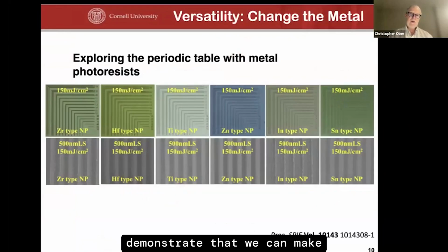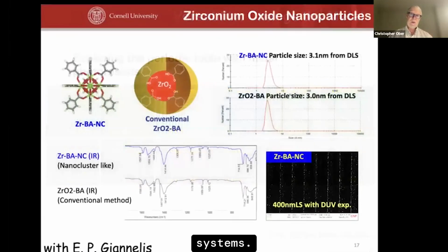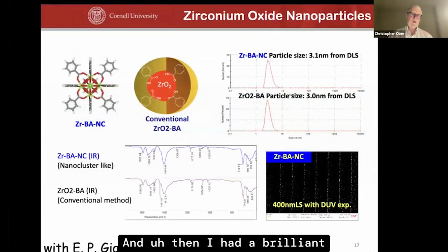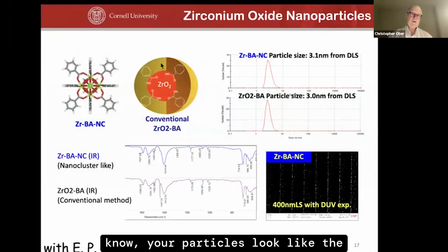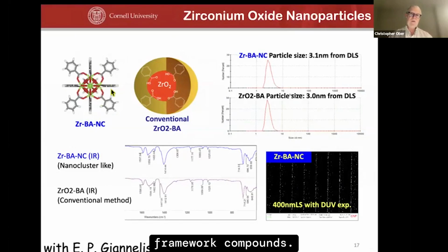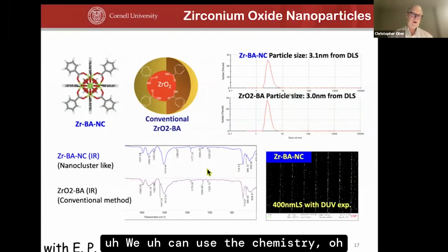And we also were able to demonstrate that we can make patterns with all kinds of oxides. This is with ultraviolet 248 nanometer exposures. It turns out at EUV wavelengths, these are much, much faster systems. And then I had a brilliant postdoc join my group who said, you know, your particles look like the apex points of metal organic framework compounds. And they have the same infrared absorption spectrum. We can use the chemistry, vast libraries of chemistries to make much more pure materials.